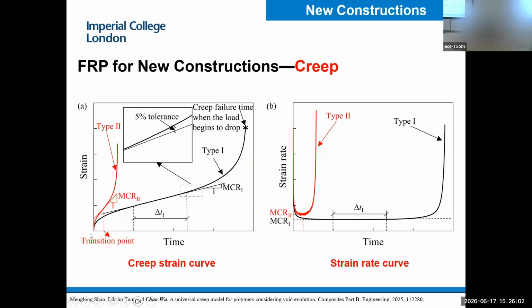The vertical axis is strain and horizontal is time. With time, it will show three stages of strain evolution. Firstly the strain increases, then the rate slows down and it enters the second stage. The creep rate becomes constant, and eventually it enters the third stage. The evolution of the strain becomes unstable, and eventually it will fracture, although that stress may be much smaller than the material strength.